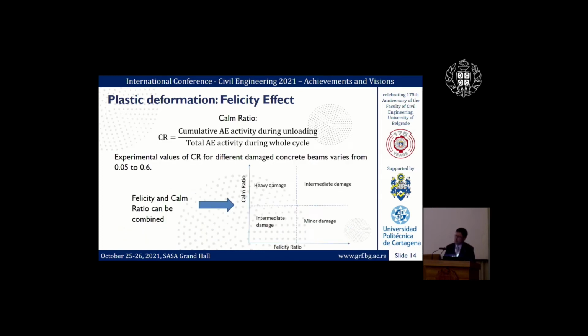Another similar damage parameter is the calm ratio. It is defined as the cumulative acoustic emission activity during the unloading part of your cycle, compared with the total acoustic emission activity during the whole cycle. In this case, if this parameter is higher, it means that more damage is present in your structure. And both parameters, Felicity and calm ratio, can be combined to make a chart, where we can see that depending on the combination of the values, we can classify the health of our structure.